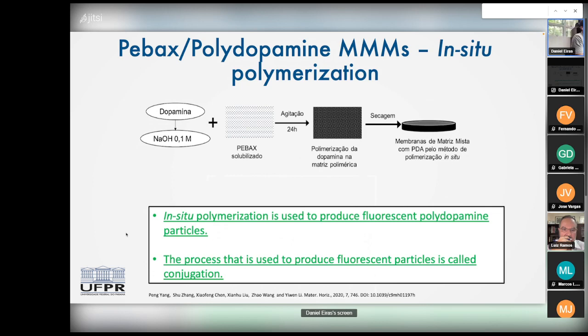sodium hydroxide and mixed that with the PEBAX in a solution. After 24 hours, we believe we have the polymerization of polydopamine inside the PEBAX membrane. So instead of doing 2 steps, we did only 1 step, and after that, we already had the polymer membrane ready to test. So what in situ polymerization does is that it reduces the interactions between the polydopamine molecules.